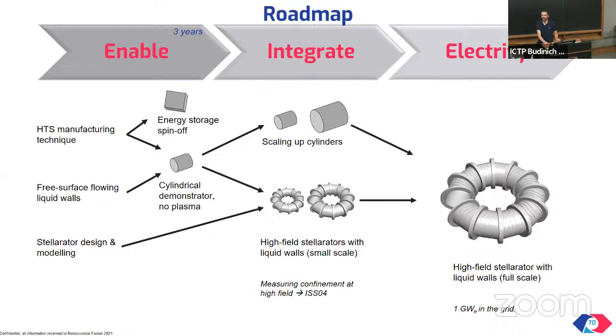In reality, the property that attracts us is not so much the ability to work at high temperature, but rather to generate strong field. The three-dimensional problem is not just the temperature, but also the magnetic field and the current. And so in this three-dimensional space, low temperature superconductors like niobium tin, niobium titanium, they occupy a small corner. HTS, exactly, they occupy a bigger space, and the one axis that we are mostly interested in is actually the strong field rather than the high temperature.